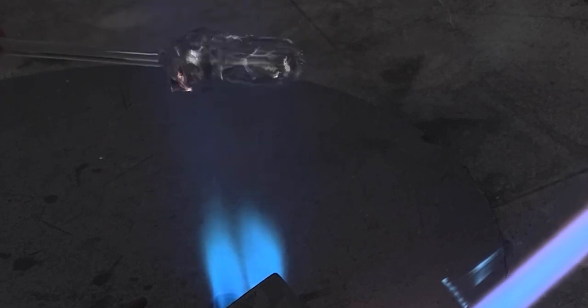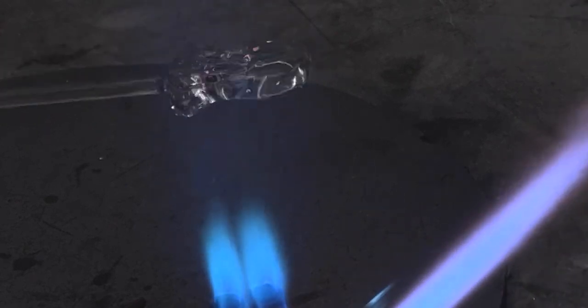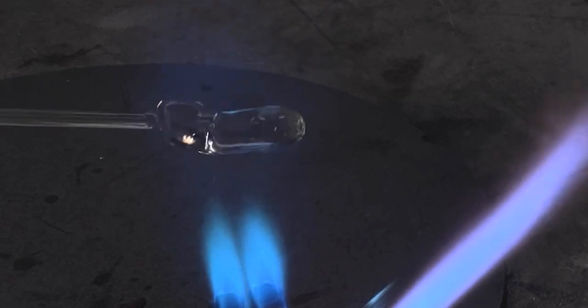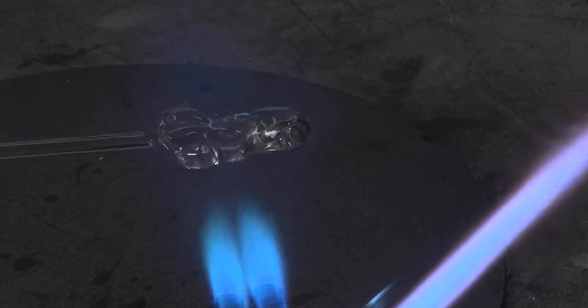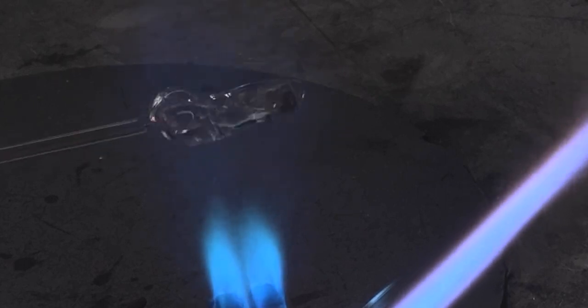Although I maintain my heat base by using the splash from the flame while preheating the next addition, it's a good idea to restore my heat base at this point in the process. This can be done by placing the piece in the kiln for a few minutes, or by reheating it using a soft, rich annealing flame. I prefer to keep a Bunsen burner handy for this purpose.